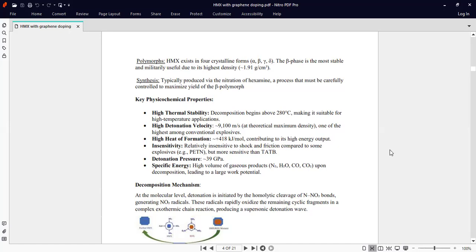Insensitivity: relative insensitivity to shock and friction compared to some explosives like PETN, but more sensitive than TATB. TATB is also known as triamino trinitrobenzene. Detonation pressure is 39 gigapascal, and specific energy for HMX is high. Volume of gaseous products like nitrogen, water, carbon monoxide, carbon dioxide upon decomposition leads to a large work potential.